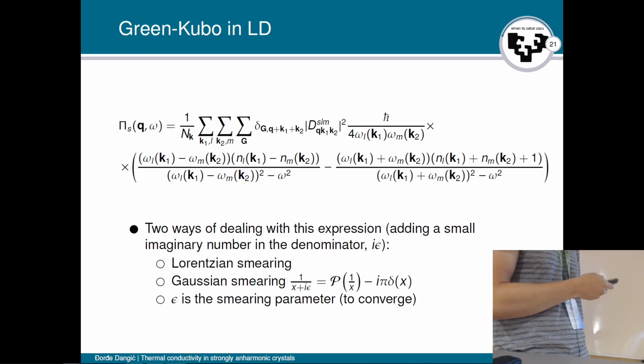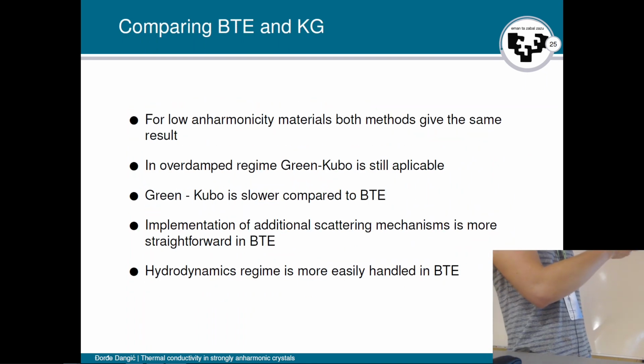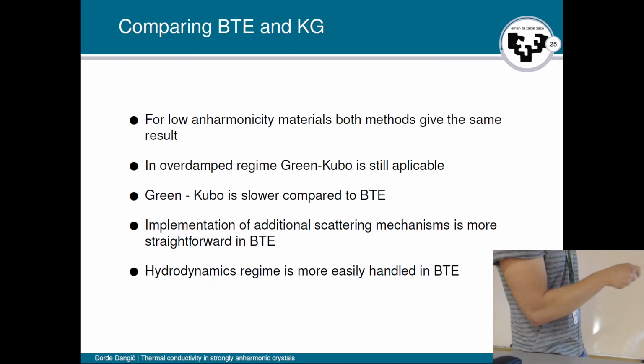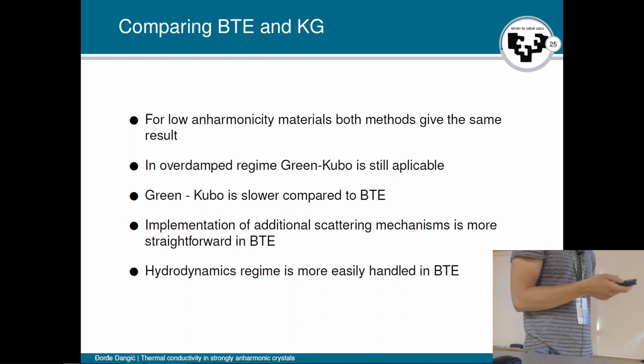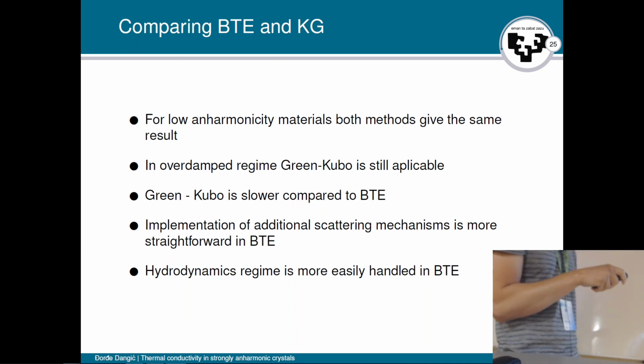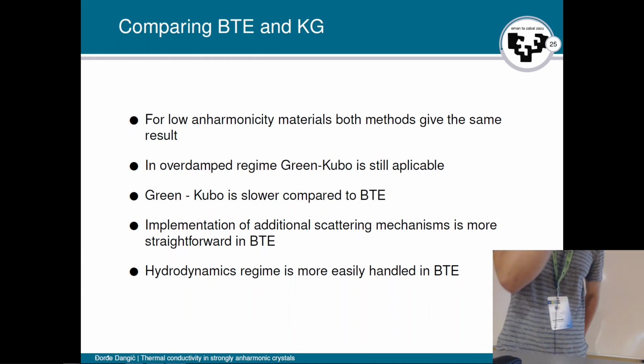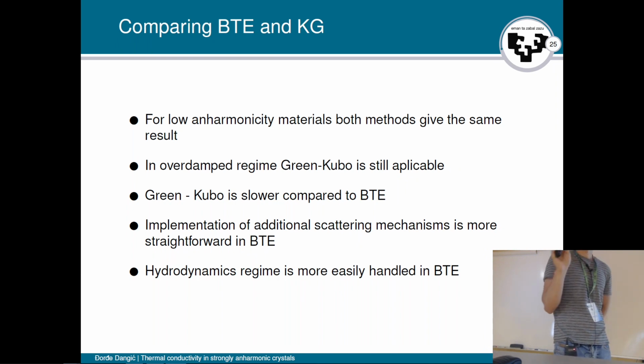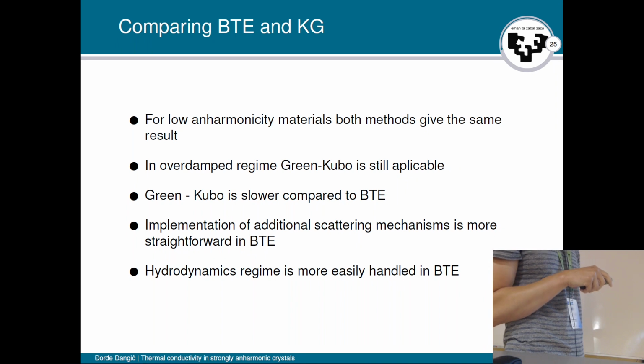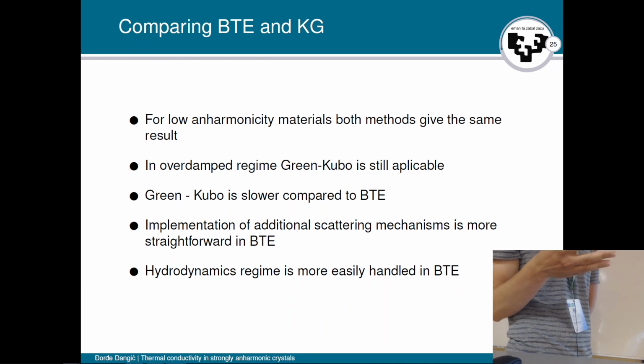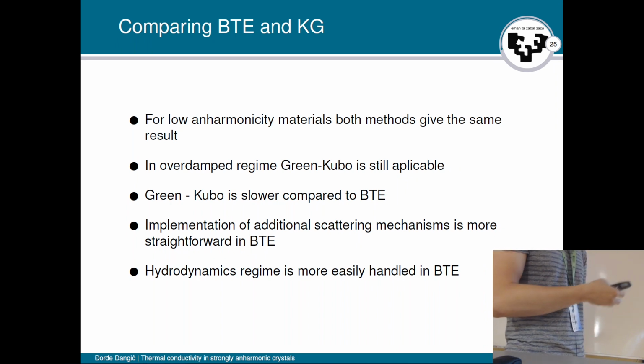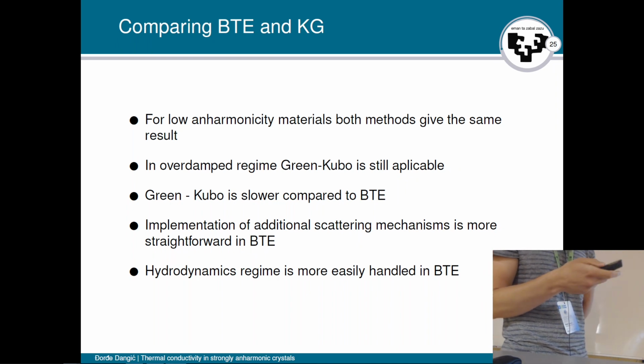And that's actually a good way to continue with the talk. We can compare the Boltzmann transport equation and the Green-Kubo, but here I'm comparing the Boltzmann transport and the Green-Kubo from the lattice dynamics, the two methods I have been talking about previously. One important thing is that for low anharmonicity materials, in the limit I was talking about before, both methods give the same result. I hope that in the hands-on session you will see that this is true. Also, in the overdamped regime, where your phonon spectral functions are not good quasi-particles, the Green-Kubo is still applicable, while for the Boltzmann transport equation we don't know. There is no reason to believe that the Boltzmann transport equation still works, but in my experience it does, so don't worry about that.